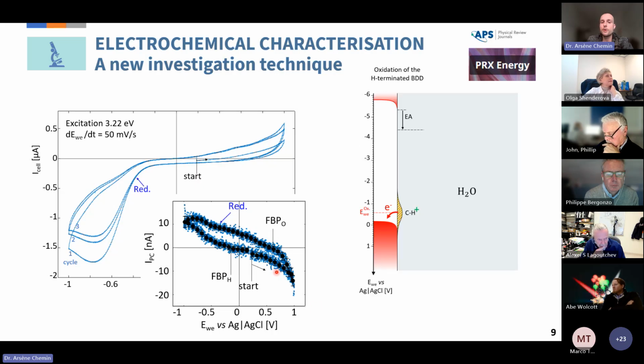And this can actually go again and again and again, because when we go back to positive potential, we will again oxidize the diamond surface. And this we were able to demonstrate happens when the Fermi level in the diamond goes below the occupied surface state at the surface of the diamond. So you can imagine that we first forced the hydrogen to stick to the diamond surface. This will create some bonding environment. But if the potential drops too low, it will pull out electrons from the CH surface states. And those CH surface groups, now positively charged, will be very reactive and will tend to oxidize.